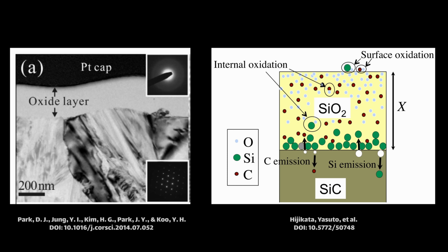And that's the key insight to this paper, even though it feels unrelated, right? What's glass have to do with sintering silicon carbide? It's relevant because silicon carbide naturally has a very thin layer of oxide on top of the surface. And that oxide layer is silicon dioxide, or silica.